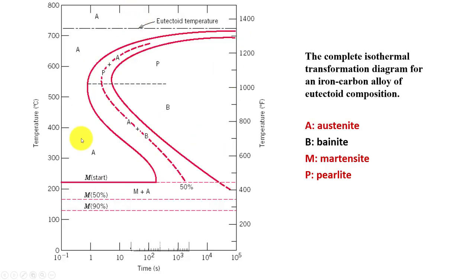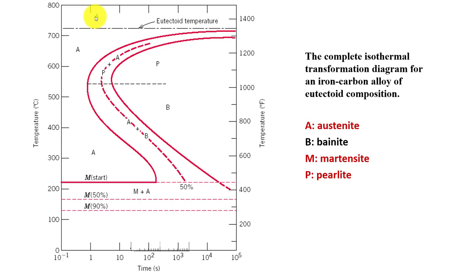This is a more detailed generic diagram that has a bit more information on things we can do with steels. Once we heat it up above the austenitic temperature — and that's going to change from steel to steel — we usually run a little hot so that we can run any alloy with the same furnaces. That gives us a little more time to get it to the quench tank. We're going to be above the eutectoid temperature, the austenitic temperature. We get it to austenite — not liquid at that point, just austenite, face centered cubic. We want to get in front of this curve. We need to quench: austenite here, austenite there, go martensite start and finish, and then it's 100% martensite. If I come down through here differently, I've got some pearlite coming out of solution with austenite and can end up with a variety of different structures.